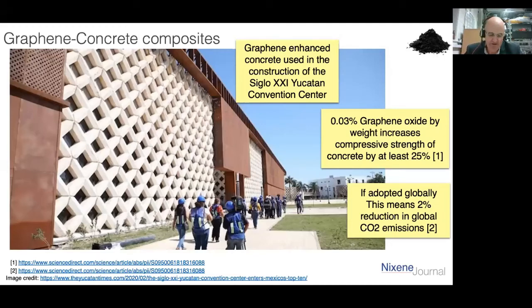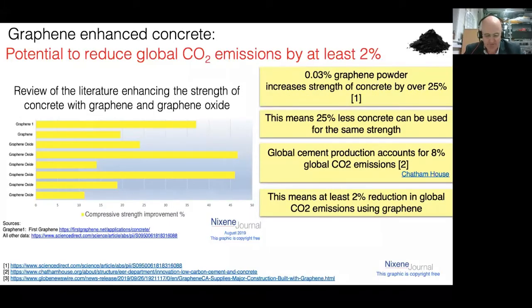And take that forward. Now, there are some variable effects, and we'll pop onto the next slide, Adrian. Because of the mixing, you need to get some control over this, as it creates variability. Adrian did some research. You can see the bar chart on the left, comparing graphene oxides and so on. At worst, you're looking at a 12% improvement, and at best, over 45%. That's potentially just the inconsistencies in how it's mixed, but that can be improved and taken forward.